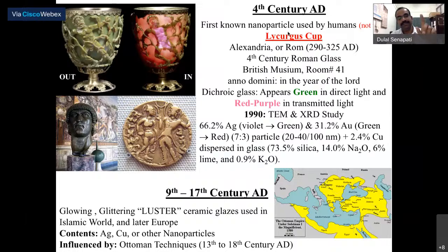Not only that, but in the right hand picture you can see that the king's chest portion is actually pink. So you think how nicely they incorporated the material so that the glass looks red, but the king's chest looks pink. This red color comes mostly from the gold. Gold absorbs the green and gives a complementary color, red. Most of the time gold nanoparticles, spherical particles, look red. And the green color comes from absorbing light in the violet region, and that's why it appears as green.